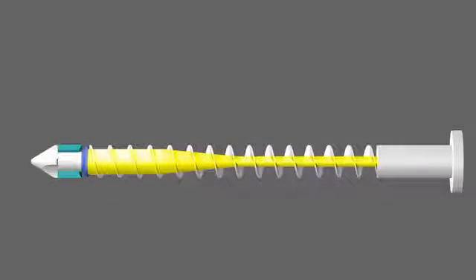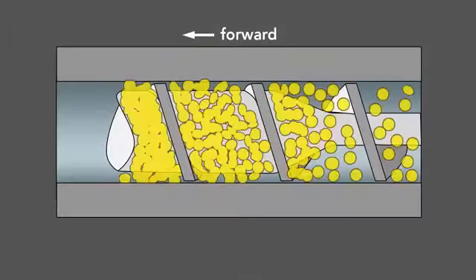And third, the screw action itself heats the plastic throughout. The shaft's diameter increases along the screw so that the distance between the wall and shaft decreases. The flights then squeeze out air as they move the plastic forward and they shear the pellets and press them against the barrel's wall. This shearing creates friction and so heats the plastic throughout. This screw-induced shear supplies a majority of the heat needed to melt the plastic, between 60 and 90 percent, with the rest from the heater bands.